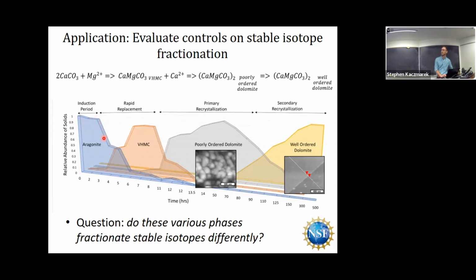When it starts to dissolve, what we produce is what we call a very high magnesium calcite, protodolomite, disordered dolomite. That forms, and then it starts to dissolve at the expense of a poorly ordered dolomite that starts forming. That then dissolves at the expense of a well-ordered dolomite. So this reaction, this equation shown here, says we start out with aragonite, we add magnesium, and we get a very high-mag calcite, then we make a poorly ordered dolomite, and then we get a well-ordered dolomite.